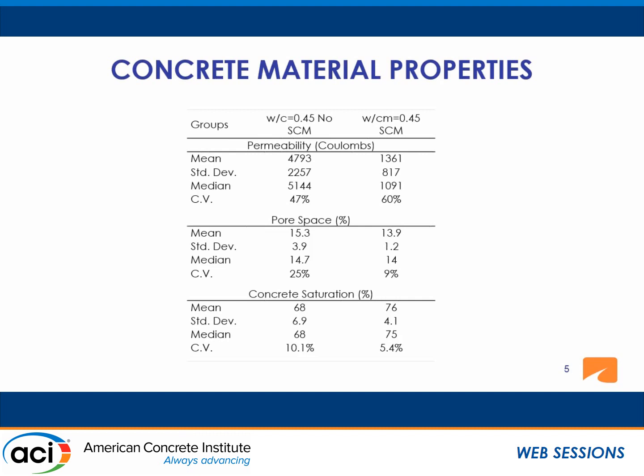And these are the concrete material properties for these two groups. As expected, the decks with the SCM, the one on the right side, showed really low permeability compared to the decks with plain cement concrete. And the pore space was also, as expected, lower: SCM concrete had significantly lower pore volume.